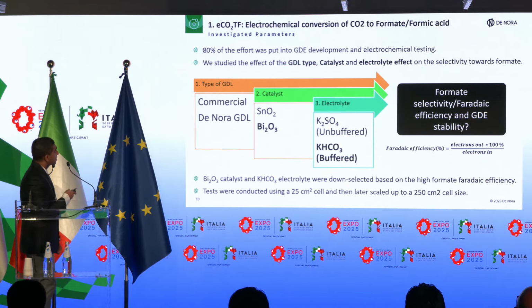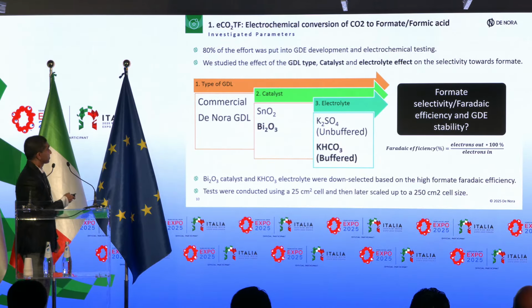So these are the main parameters we investigated in this project. I want to mention that 80% of the effort was put into developing the gas diffusion electrode component and electrochemical testing. Here we studied the effect of GDL type, that means gas diffusion layer, and the catalyst and electrolyte effect on the selectivity towards formate.